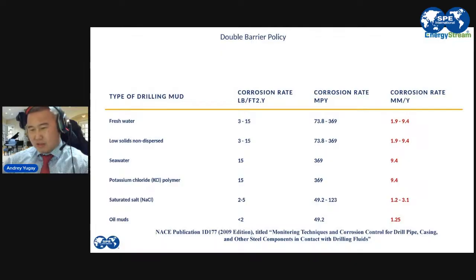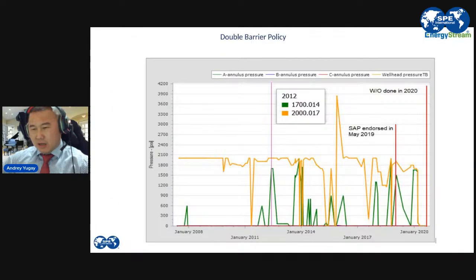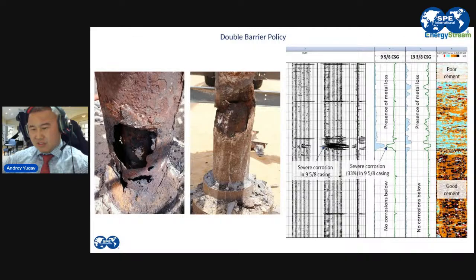What about the conditions in between? How we can prevent? You see on the right side, there is a corrosion, and this corrosion actually happened at 950 feet. Top of cement is at 950 feet, and then we got this corrosion happening. How we can prevent this, basically? Yes, if our outer casing would be coated externally, it would not help us at all. If our inner casing, 9 5/8, would have been coated externally, yes, it would help. But still, the corrosion of 13 3/8 would happen. And currently, we don't have internal casing coating service on the market.